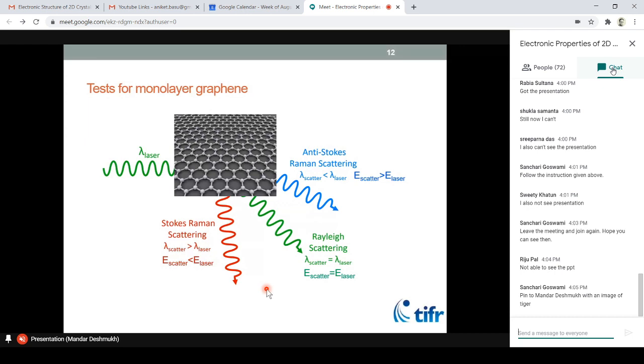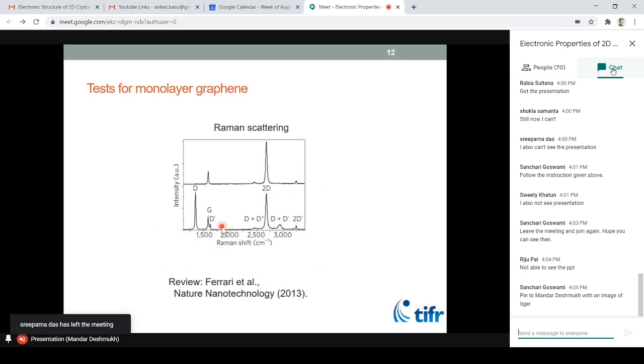So the Raman effect is the foundation of a lot of scientific experiments and technologies in chemical sensing. So we have to feel gratitude towards Sir C.V. Raman for this amazing discovery. And so if you look at the spectrum, you can actually identify, which is watertight evidence, that this is 1 atom thick. Not just that, you can identify some defects inside the material as well. Okay, so Raman scattering is a way for me to know for sure. So once we see this, we actually test and confirm that it is 1 atom thick by essentially Raman scattering.